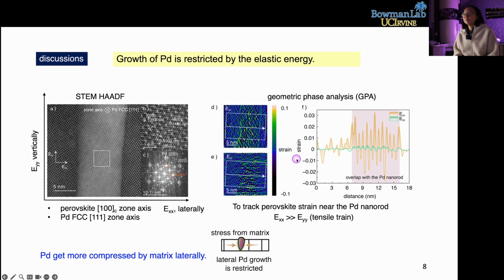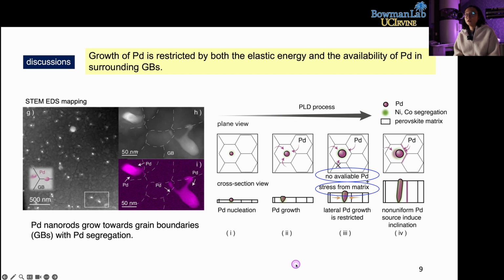So from the GPA analysis of the perovskite matrix, we can see the matrix has a very strong tensile strain at the region overlapped with the palladium nanorod, in the horizontal direction more than in the vertical direction. That means the perovskite matrix gets highly tensile stressed by the palladium nanorod in the x direction. Oppositely, the palladium nanorod gets compressed by the matrix in the x direction, way more than in the y direction. That means the palladium, the exsolved phase, gets more compressed by the matrix in the x direction. So like this schematic shows, the stress from the matrix will confine the morphology or growth of the palladium, so they may form the nanorod morphology.